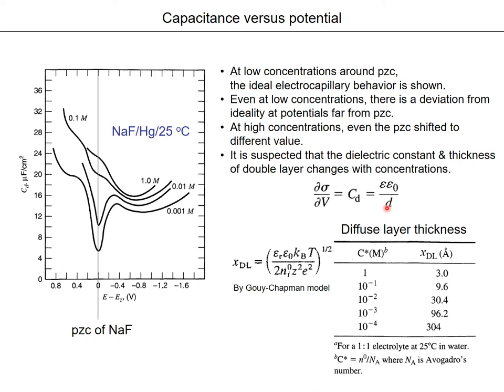So those two things, the dielectric constant and the double layer thickness, could be functions of concentration. So we could have some change in the curve of capacitance versus potential with concentration, even with the same identity of the salt or ions. For example, XDL is the diffuse layer thickness, and this is a function of the bulk concentration of ionic species. It means XDL is inversely proportional to the square root of the concentration of ions. This comes from the Gouy-Chapman model, and we will learn about that in the following chapter.